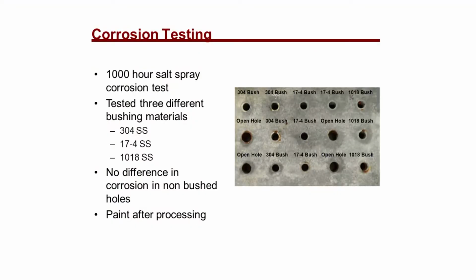So we did a 1,000-hour salt spray, and what we found is that the base material didn't corrode more because of the presence of the bushing. It just corroded in an even manner with it. So you just treat it like you would any material. If you have to paint it, then you paint the bushing as well. So there's really no impact that we could see.